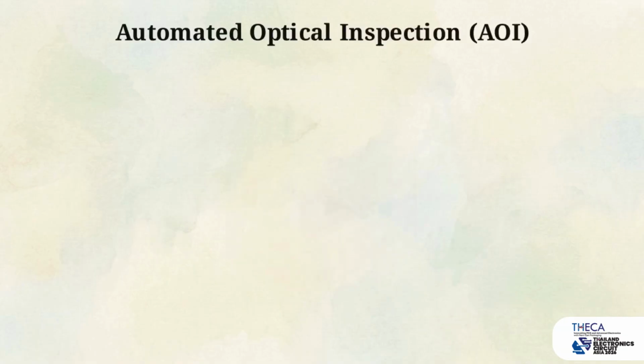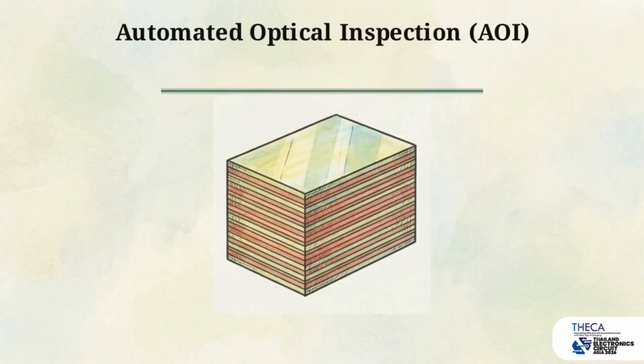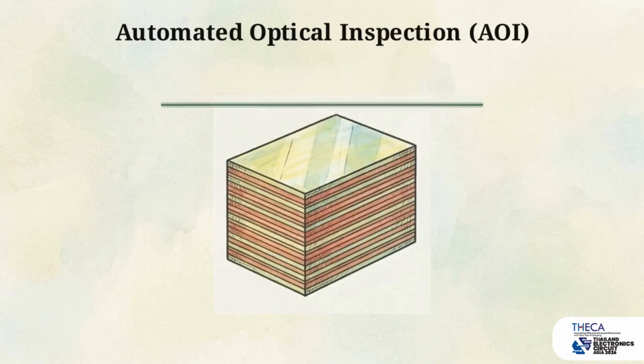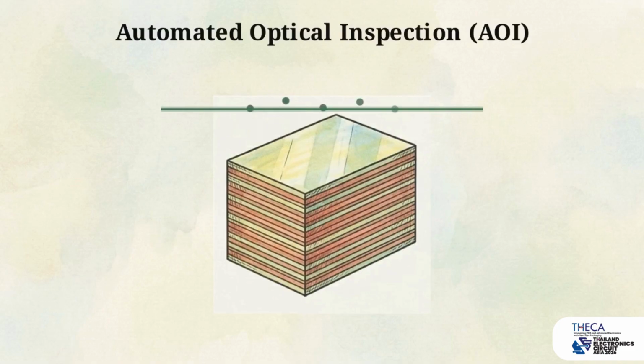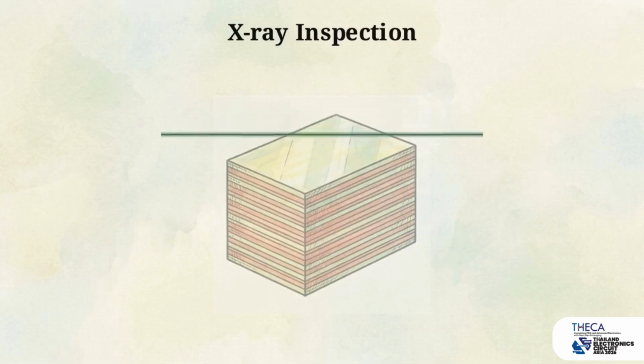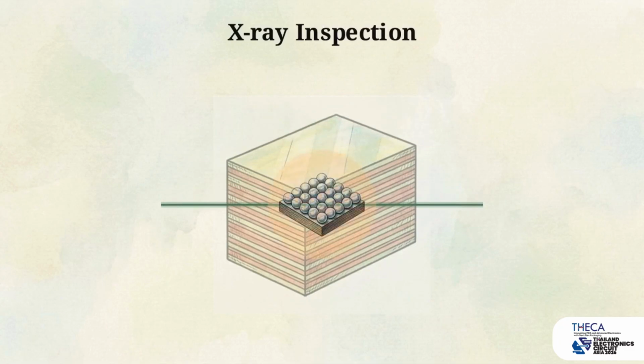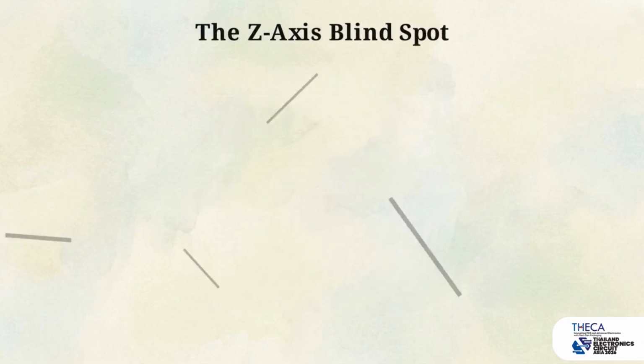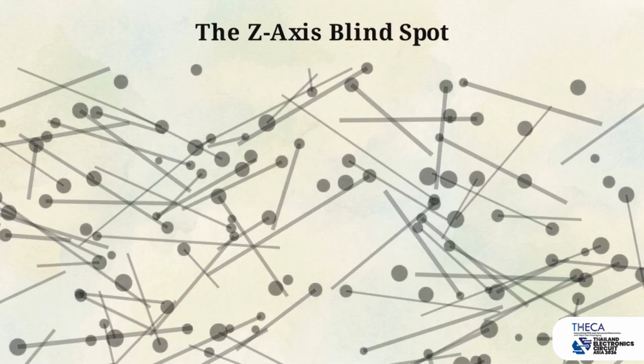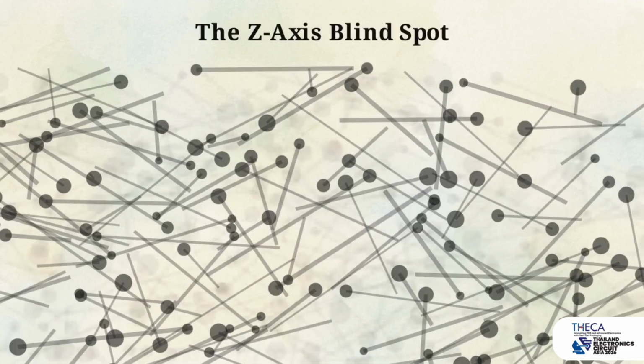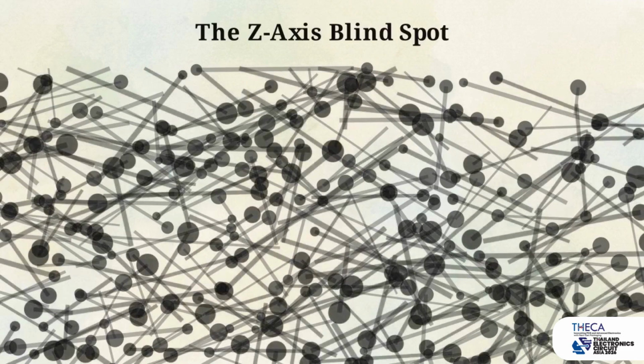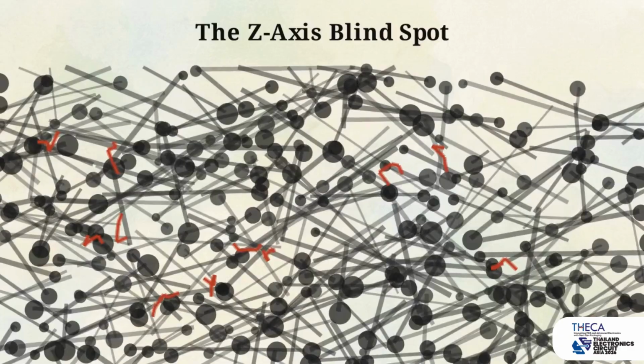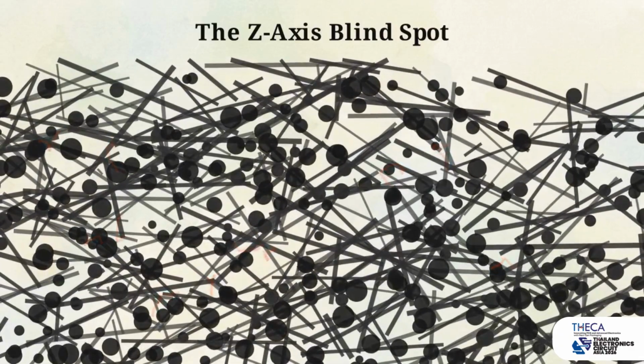To understand why tests fail, look at automated optical inspection. AOI is restricted to the top layer. It verifies external components and smooth solder joints, but sees nothing beneath. X-ray attempts to solve this by penetrating fiberglass to view hidden structures, like BGAs. The problem is X-rays analyze density. They struggle to separate structures overlapping tightly along the vertical z-axis. In modern high-density boards with 40 layers, the sheer density of copper vias effectively blinds the X-ray. Microscopic separations vanish into the solid gray background geometry.